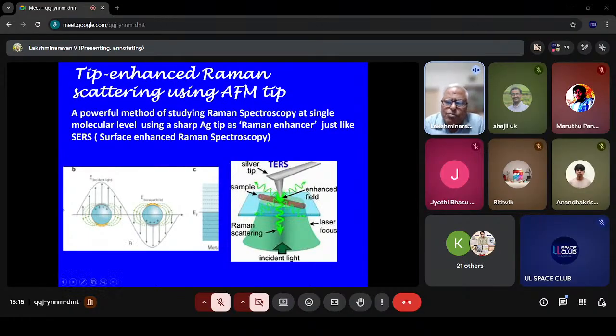So what it really means is you bring an AFM tip, a cantilever with a tip. If the tip is, for example, silver, which is a very common material used in enhanced Raman, and if you apply a laser light at that location, the electromagnetic field is enhanced several orders of magnitude. This is due to the surface plasmons which were created on the silver surface.